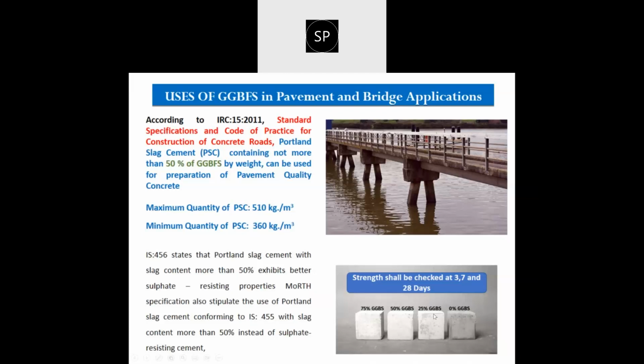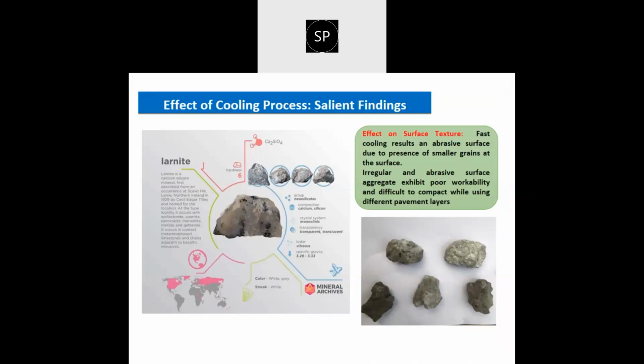So here, in terms of how you will design with different GGBFS content while you want to cast a cube, first of all you have to cast a concrete cube with 0% GGBFS, meaning with conventional OPC or PPC cement. Then you can replace that OPC and PPC cement by 25%, 50% and 75%, and check how the strength is changing. Depending upon that, you can fix the quantity of GGBFS which can be utilized as a substitute for conventional OPC or PPC cement inside the concrete mix. In comparison to the conventional concrete cube, these cubes will be milky white in color, as you can see in this photograph. Therefore it has a good appearance in comparison to the conventional cement based material.